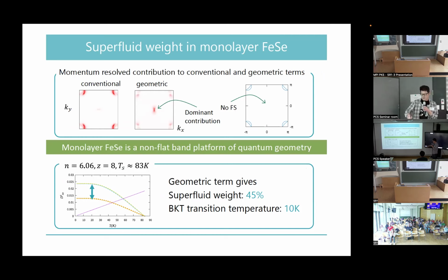So this figure shows the temperature dependence of the superfluid weight in the model, and the difference between these two lines is the contribution from the quantum geometry to the superfluid weight. So according to these results, we conclude that almost half of the superfluid weight in this system comes from the quantum geometry, and the BKT transition temperature is enhanced to approximately 10 Kelvin in this system. So the quantum metric is important for the high temperature superconductivity in this system. Okay, so maybe the time is up.